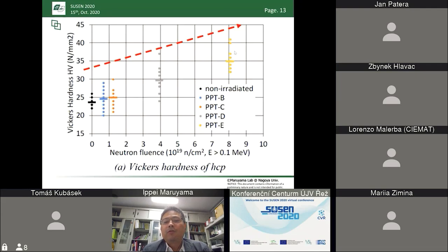This can be explained by the probability that neutrons give some defects to the cement hydrates. But at the same time, due to the high amount of water and the high surface area, we see water content inside of the specimen. And probably after getting the defects, the hydrates will dissolve and precipitate again, and the defects will be filled through the dissolution and precipitation process. So therefore, the cement paste is quite durable, while the aggregate is very sensitive to the neutron irradiation.